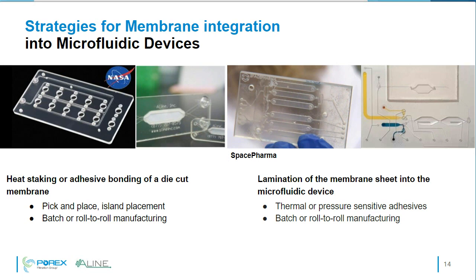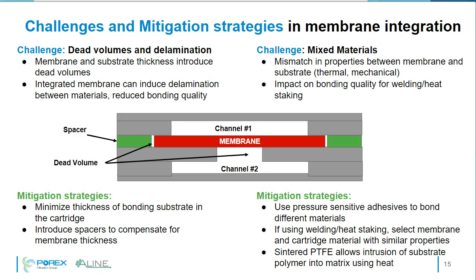The choice of which strategy to apply really depends on the application, so it's something that typically gets analyzed at the beginning of every development program, but there are pros and cons to each that can be considered in this integration step. Once the membrane is integrated into the device, there are a few challenges to keep in mind. The first one that we want to oversee here is the dead volume and the delamination. Whenever a membrane is introduced into a microfluidic stack, there are thicknesses that need to be taken into account, and they can introduce dead volumes. A couple of examples are shown here in the schematics. Another thing that can happen is that the membrane itself can induce delamination between materials because of its own thickness, and that can reduce the bonding quality.